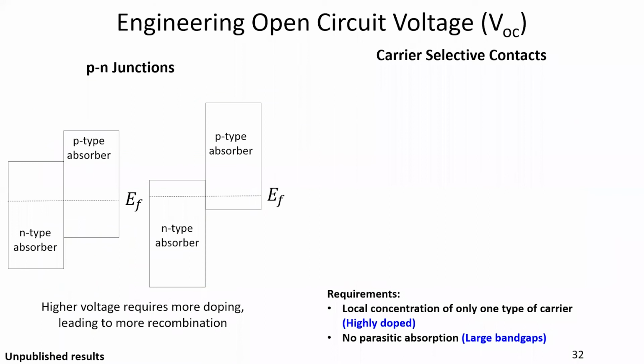We have attempted a little bit to this end. The obvious thing to do would be, if you have a PN junction with some band alignment, to maximize that band alignment or the built-in potential, if you start doping the p-side more and the n-side more, and therefore the built-in voltage within your diode keeps increasing. That should then lead to an increase in your open circuit voltage. It turns out that is very difficult to do for very thin materials, and also if you dope your absorbers heavily, you're going to create more recombination losses because dopants are going to create defects, right?